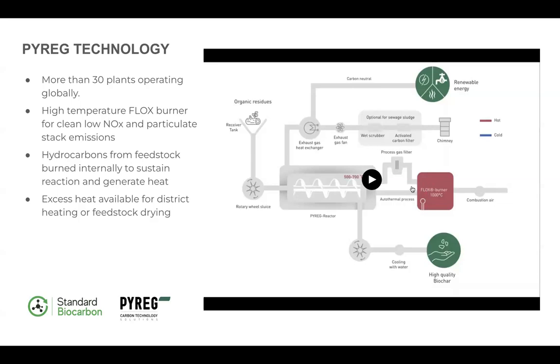You can see at the bottom here, out of the reactor, the biochar is discharged and sprayed with water to avoid combustion. And as I was saying, we can adjust the amount of water sprayed into the biochar at the end, depending on what the customer would like. You're left with biochar that we'll be bagging in 2 cubic yard super sacks. And we hope to be able to work with a contract bagger to provide other options for bagging, such as 1 or 2 cubic foot bags of biochar.